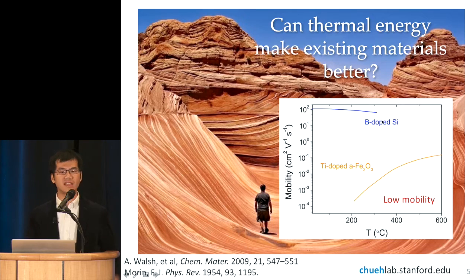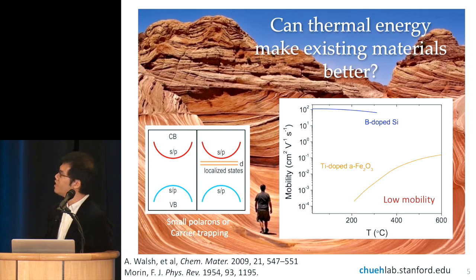And as you can see in silicon, the mobility is largely independent of temperatures, very high, about 100 centimeters squared per volt per second. But for iron oxide, it's immeasurable at room temperature. And with increasing temperature, you slowly climb up, but you need to go to several hundred degrees Celsius. It turns out that this is a very general phenomena in metal oxides because the d orbitals in oxides, especially in the transition metal oxides, are typically very narrow. So this gives rise to rather low electron mobility, and this really limits the performance of this material.